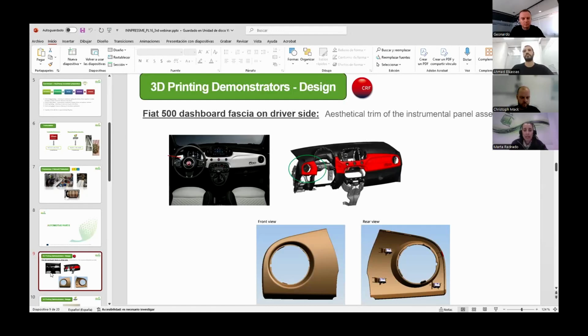What we did is the aesthetical trim on the dashboard, the one you can see here on the left. That's the one we decided to print. It is on the driver's side. Nowadays, this air vent fascia is manufactured via injection molding using polycarbonate and ABS materials. But since the center style is often asking for a special series with an associated low volume production, the idea was to produce this trim by using additive manufacturing instead. So it's a cheaper solution and it's faster than having to produce a mold specifically for these short run pieces.